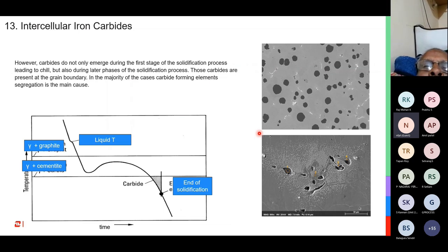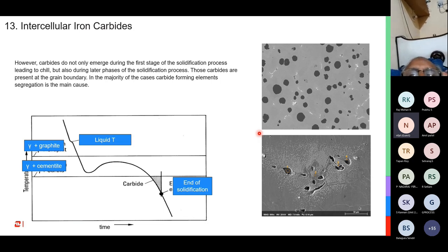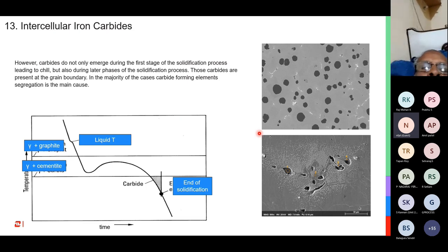So these elements have a tendency to segregate towards the last freezing zone, and when they segregate there, they cause some amount of carbides to form. We usually do not find these kinds of carbides, but suppose you have a casting where you are doing a through hole, where you have to drill through the core of the casting. We sometimes encounter that tool life becomes poor when doing a through hole. And why does it happen? Because the tool or the drill is encountering hard phases towards the center of the casting. And these are called intercellular carbides, intercellular iron carbides, which are present towards the center of the casting.